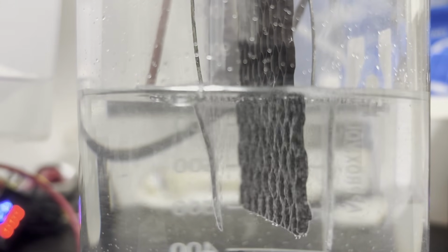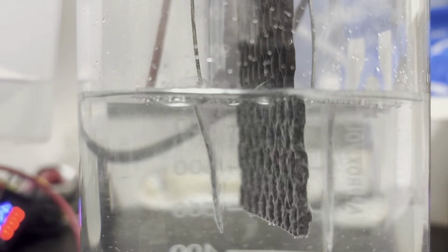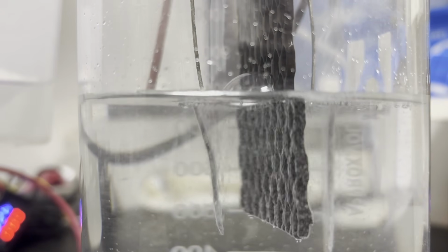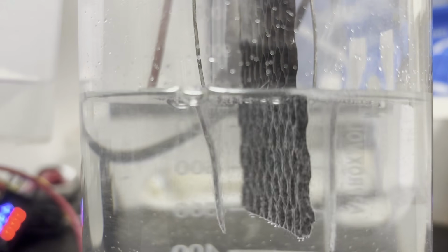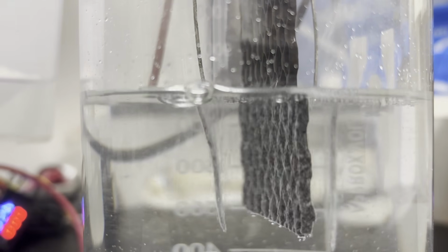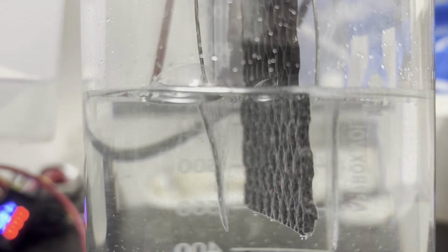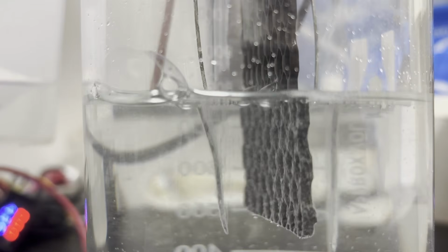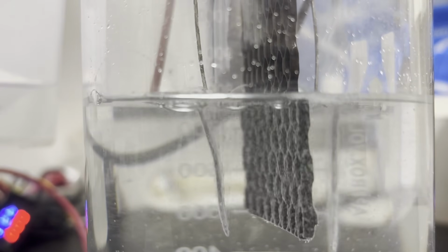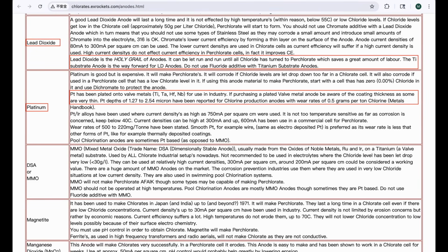As we may be familiar with, producing chlorate from chloride can be done using simple anodes such as graphite or titanium substrate mixed metal oxide electrode, but they cannot produce any perchlorate, perhaps because of their low oxygen evolution overpotential that oxidizes water to oxygen instead of chlorate to perchlorate. Instead, we must use an anode material having high oxygen evolution overpotential, as well as electrolyzing with high anode current density to promote chlorate oxidation instead of water oxidation. Titanium substrate lead dioxide, pure platinum, and boron-doped diamond anodes can oxidize chlorate to perchlorate.